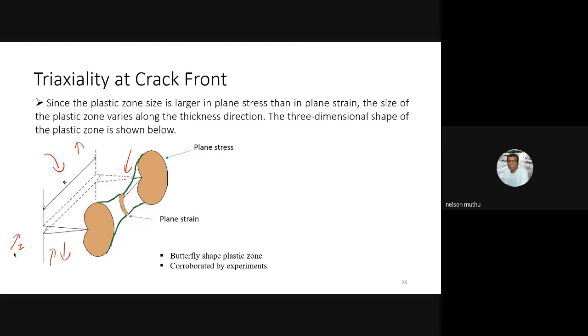The surfaces which have the z-axis as a normal are going to behave like a free surface, because there is no external traction on them. The surface that is visible to you, one in front of you, one behind the specimen, is subjected to a plane stress condition. Why am I saying that? Because sigma zz, the applied traction in that direction, is going to be 0. Therefore, close to the surface, one principal stress is 0, and your material is behaving like plane stress. If the material is behaving like plane stress, the size of the plastic zone will be considerably higher.